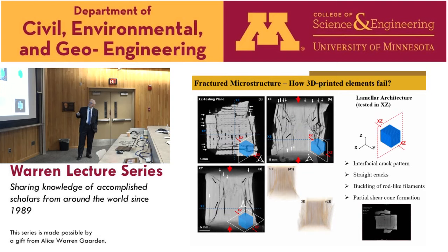And this is testing in another direction. And again, if you look at the mode of failure, you can see that again the damage sort of tends to be along the weak zones. Weak zones are the zones between the filaments. We actually are working right now on trying to reinforce those weak zones by using short fibers that will be helping bridging some of those gaps. And you can extrude the fibers at the same time as you're extruding the filaments. You can use another nozzle to put the fibers on the deposited layer of filament. So that technique allows you to modify, allows you to be innovative, I think.